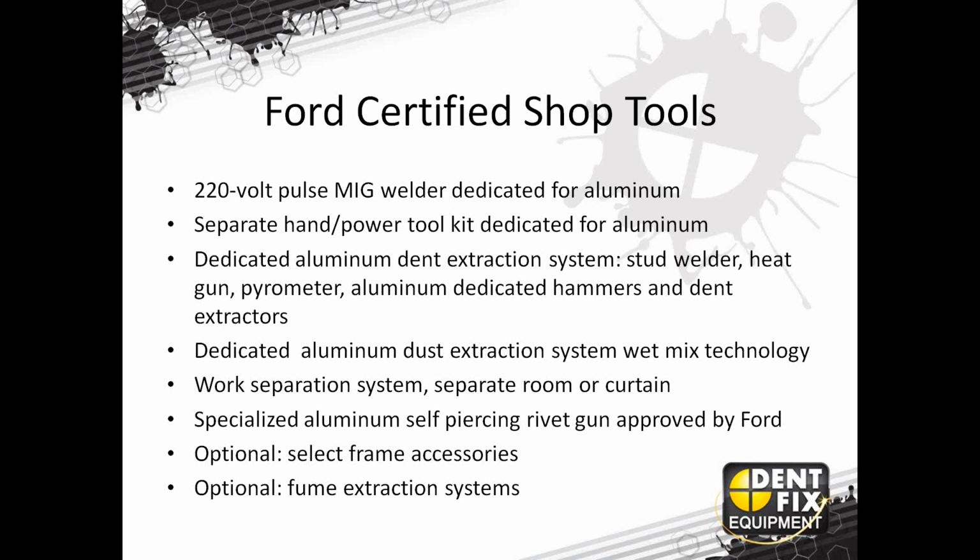Now, if you use a heat gun that has a digital temperature set on it, on the back panel, then you're able to control that using that because it is a general area of temperature that you need to get through, again, 400 to 600 degrees. And if anyone ever reads the instruction sheet on an infrared thermometer, please note that it does not work on reflective surfaces. So you'll need to put a magic marker or something like that to get a proper heat rating on it.